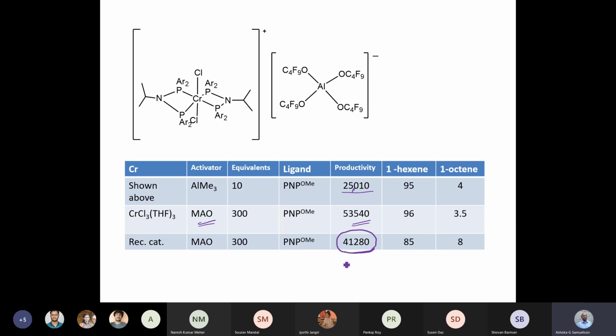reduces in its activity, and that is quite common, but that tells you how efficient the catalyst is. But this is a very large number. This productivity per mole of the catalyst, you have 41,280 times ethylene moles converted into the hexene and octene. And also you notice that the selectivity is incredibly high. You get 85:8 of hexene to octene. Tetramerization is happening, but to a small extent.